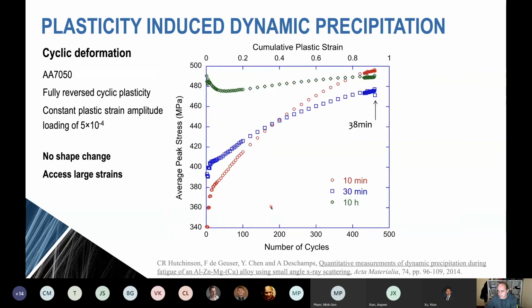Another interesting opportunity is to use cyclic deformation, and cyclic deformation is interesting because you can apply the plasticity without a macroscopic and final shape change to your material. And so this is an example of applying, again, a 7000 series, 7050 in this case, aluminium, zinc, magnesium, copper alloy, where we have applied cyclic plasticity at room temperature under a particular type of loading. It's constant plastic strain amplitude.